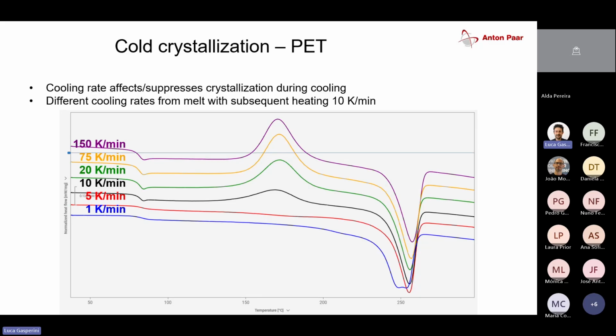And in this case, the cooling rate affects very much or suppresses the crystallization during the cooling. So in this, we have heated the sample from room temperature up to about 300 degrees, every time 10 degrees a minute. But before, we cooled the sample down from a melt with several different cooling rates from 1 up to 150 degrees a minute. And there are two main effects that you can see. One of them is in the area between 150 and 200 degrees, where with the lower cooling rates, we see no effect happening here. But the higher the cooling rate is, starting from 10 degrees a minute, we see an exothermic peak being shown, an upward facing peak.